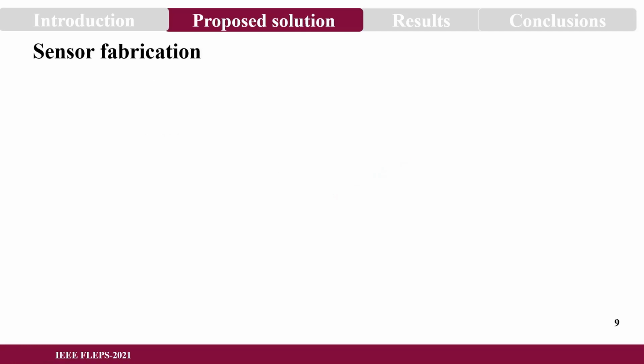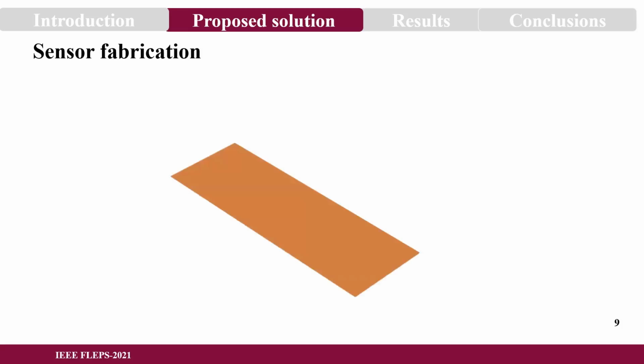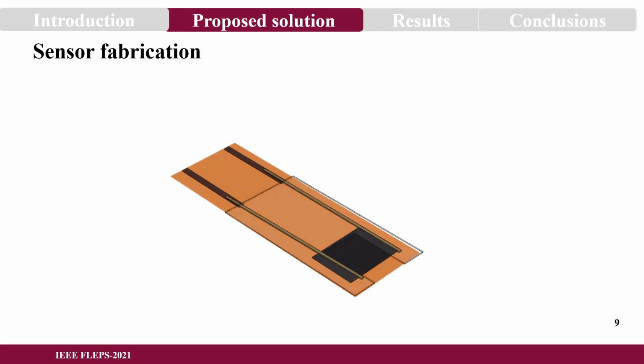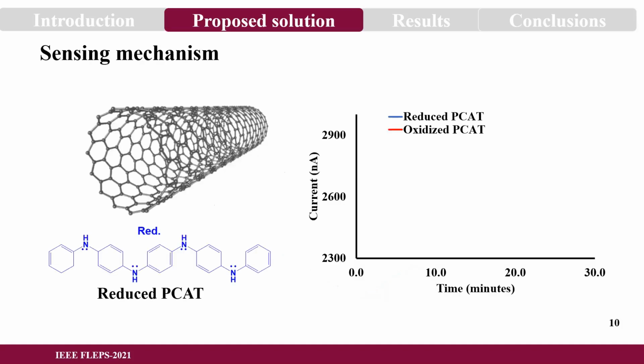Here, the sensor fabrication is done on Kapton tape, which provides a flexible substrate. On top of that, we have used graphene-like carbon as the sensing material, in sheet format, which was again patterned using xerography. Finally, the gold leaf was put on top of the sensor to make the electrical contacts between the GLC sheet and our final electrical connections, which were made using copper tape. Finally, the sensor area was defined using parafilm.